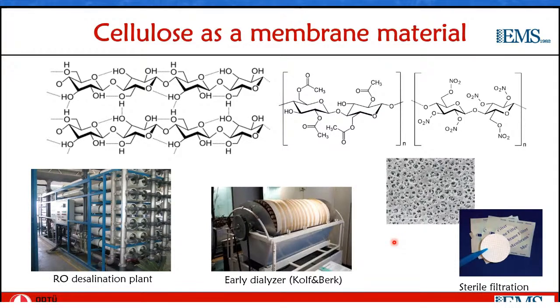For instance, the cellulose acetate RO membranes were replaced by interfacially polymerized polyamide membranes with better permeance and better resistance against biological attack, but poorer chlorine tolerance. Microfiltration and ultrafiltration membranes were replaced by PES and PVDF with better thermal, chemical, and biological stability, but were more prone to fouling. And hemodialysis membranes were again replaced by polyether sulfone or polysulfone with better biological inertness compared to cellulose.